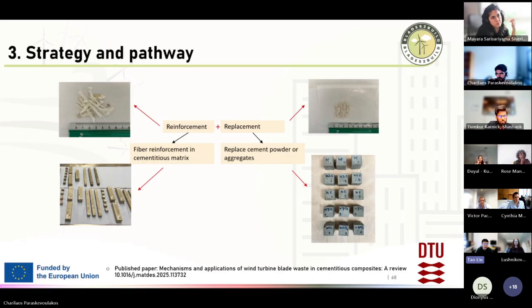Here in DTU, we have two pathways as well, replacement or reinforcement. Replacement I will not describe, but we sieve and crush the powders into the cement paste. And then as a fiber reinforcement, as we see in the picture on the left, we do it in a mortar to test the mechanical performance, flexural and compressive strength, and also further test the shrinkage and alkali silica reaction expansion on the mortar samples as well. Please next.